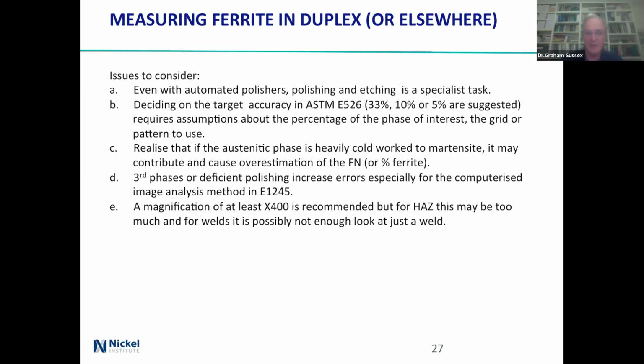And that really makes some assumptions about what phase you're interested in. So are you going to have a square grid, a round grid, whatever? Because you do want to make sure that you don't go intersecting multiples. And if you do cold work to get a heavily worked martensite, you may contribute. So if you're using a ferrite meter, you'll get a number. And third phases, or lousy polishing, are going to give you errors, especially if you're doing computerized image analysis. They recommend at least 400 times 400. Well, the problem with times 400 is that in a HAZ, that may be too much. And if you're right in the middle of the weld, then how do you just look at the weld?